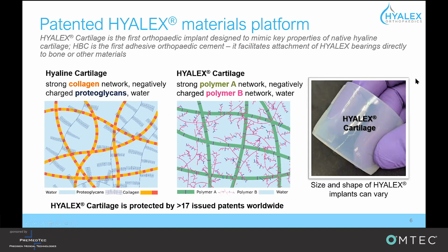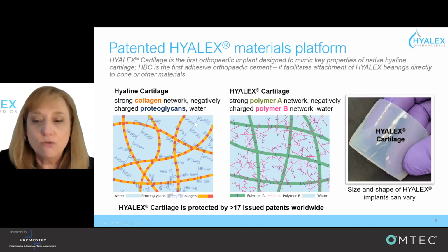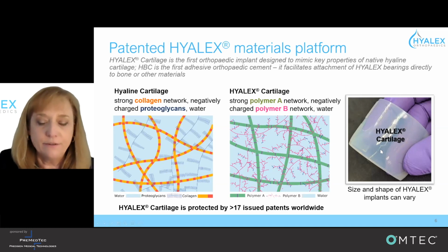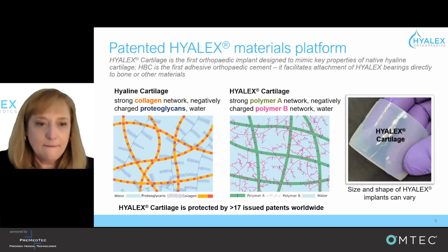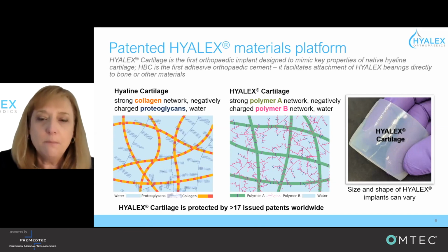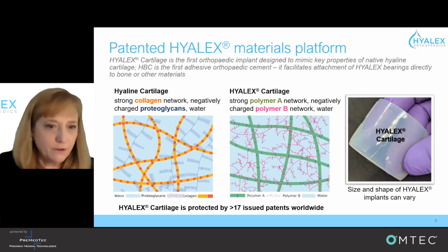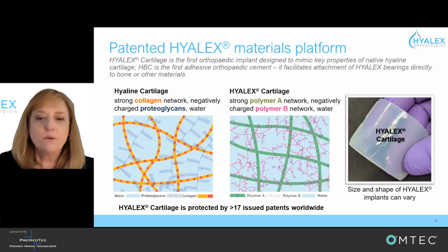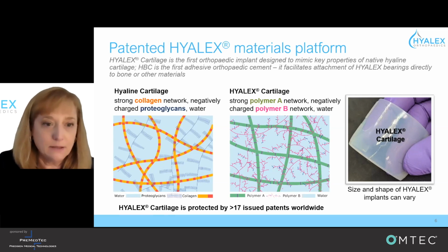On the far right-hand side, you see a sample of HYALEX cartilage. HYALEX cartilage has a gradient structure, so it's got a very smooth, lubricious, hydrophilic bearing surface, and then it's got a hydrophobic back surface to allow for attachment. The size and shapes of cartilage implants that we can make with HYALEX cartilage can vary and depends really on the application. The HYALEX material platform also includes an adhesive that we developed specifically for the fixation of HYALEX. The adhesive forms a strong, permanent bond with the bearing, allowing a wide variety of implant designs to be possible.